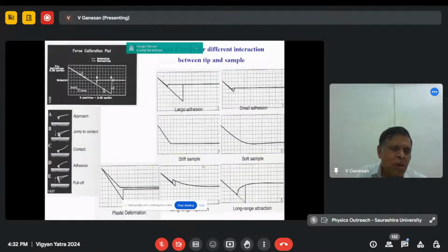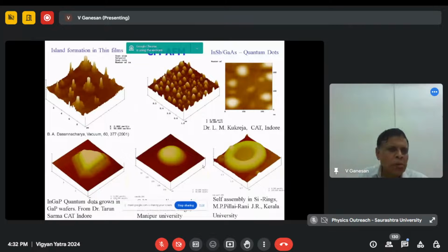The only problem is that these nanotubes or nanoparticles, etc., should be held on a substrate very rigidly to do all this work. I will also show you, depending on the time available. So, very beautiful island formation which I showed you here. Actually, this is from the thin film unit, and it shows you something like about 15 nanometers thickness, etc. You can see that each top of the island, called columnar growth actually, is about 500 Angstrom. And in between, nothing is there.